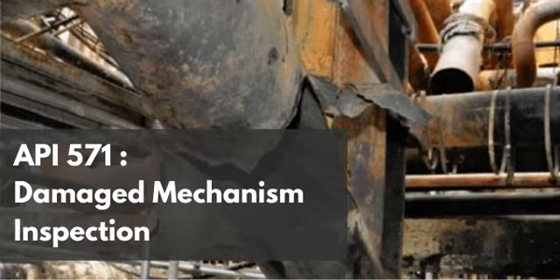Let's explore that. If I just wrap a narrow 3-inch heating band directly over the weld and crank it to 1175 degrees, what happens to the steel right at the edge of the heating band? You create a massive, severe thermal gradient.